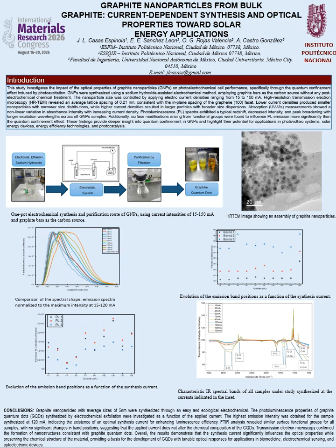The four investigated GNP samples, with mean sizes of 2.44, 3.66, 3.91, and 6.80 nanometers, exhibited broad PL emissions peaking at 465, 475, 505, and 535 nanometers, which correspond to energies of 2.66, 2.61, 2.45, and 2.31 electron volts, respectively.